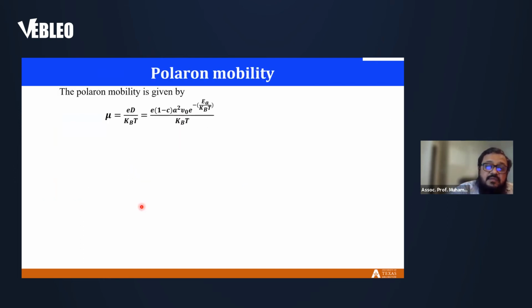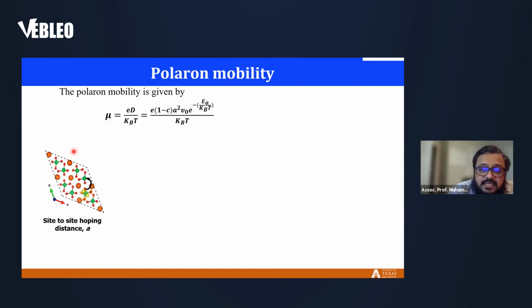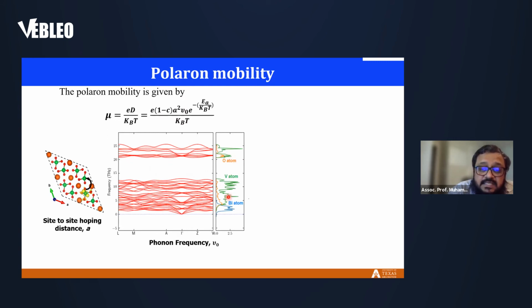Then we get some numbers for the polaron mobilities for both of them. For that, we use an equation which is called the Einstein equation for transport. e is the electronic charge, 1 minus c is the hopping probability, a is the hopping distance. The quantity that we need to calculate now is this nu zero, which is the phonon frequency of the polaron site, if it is anion or cation. To do that, we calculated the phonon dispersion plot and phonon density of states. From there, we get the typical phonon frequencies of vanadium and oxygen. With that, we calculated the polaron mobility. Again, it shows like the activation barrier. Hole polaron mobility is higher, at least 3 times higher than the electron polaron mobility.